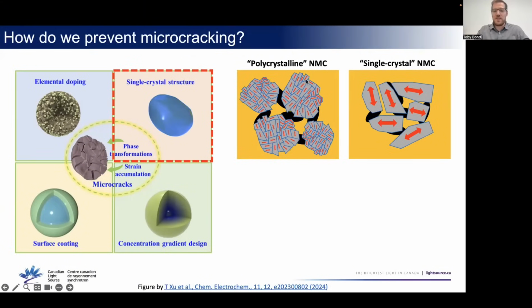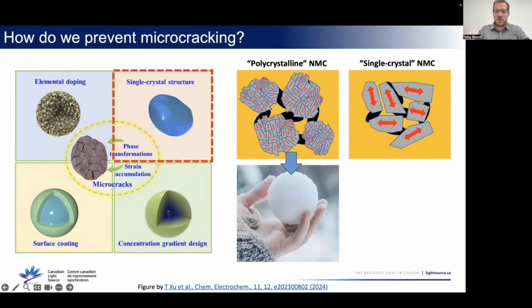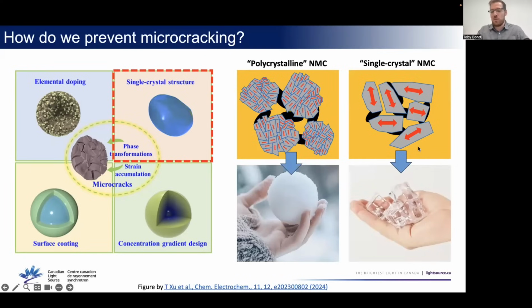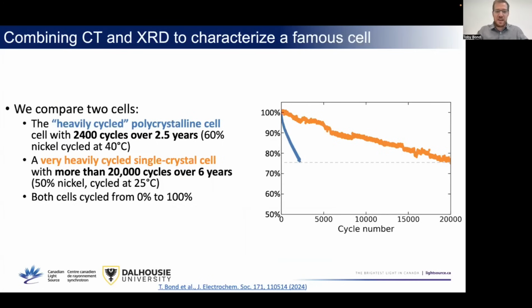So since we have this cracking happening along these boundaries, one way to get rid of that is to just not have the boundaries anymore. It sounds pretty straightforward, and it turns out it's very, very effective. So if you think about these polycrystalline particles as being a snowball, a single crystal particle is more like an ice cube. It's just one big solid crystal, and it's much more durable. If you squeeze a snowball with your hand compared to squeezing an ice cube, it's a lot easier to crush the snowball than it is to crush the ice cube. So that's a good analogy for how these materials behave.